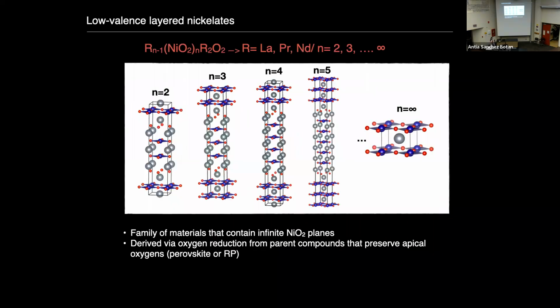And the family of materials that realizes this paradigm is the family of materials that I like to call low valence layered nickelates. This is a family of materials that all contain infinite nickel-oxygen 2 planes in analogy to the copper-oxygen 2 planes of the cuprates. So you see those guys all the way here. This is probably the bigger one, so easier to see. In blue, we have the nickel here, in red, the oxygens. So you see how we have exactly the same type of planes that I showed you before for the cuprates.